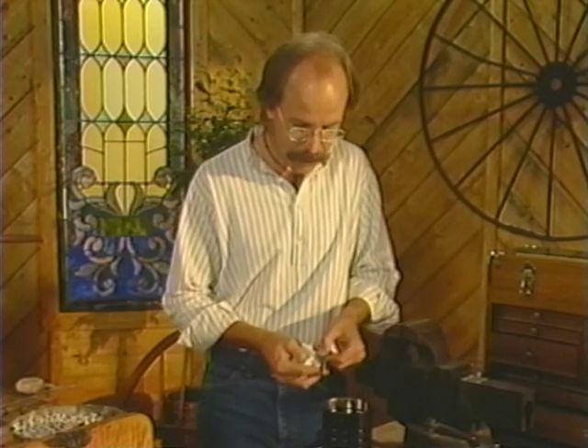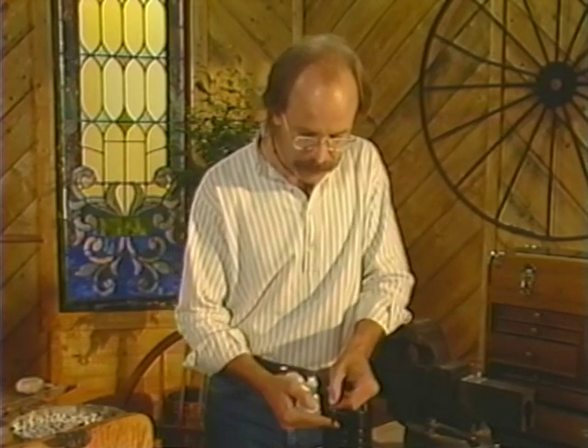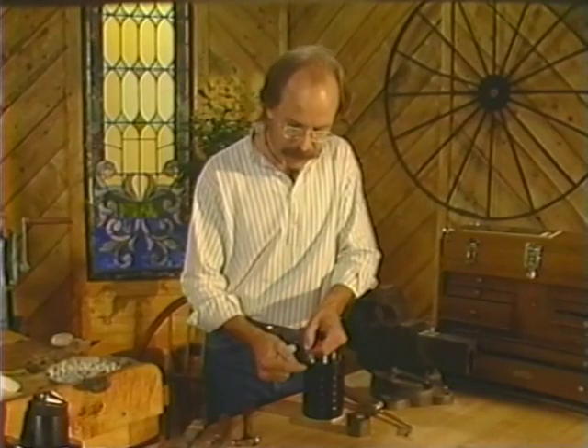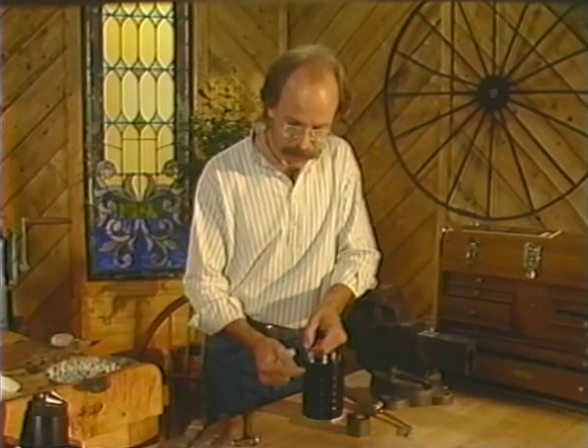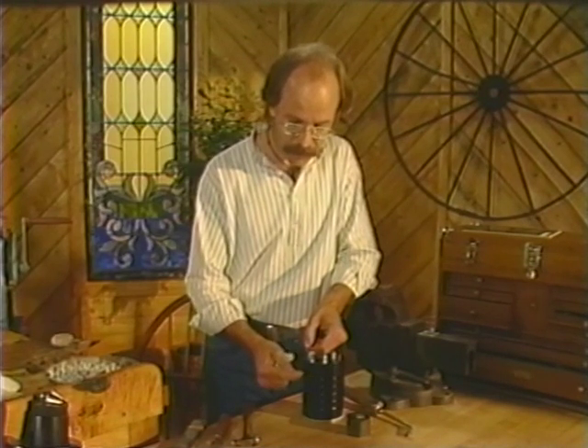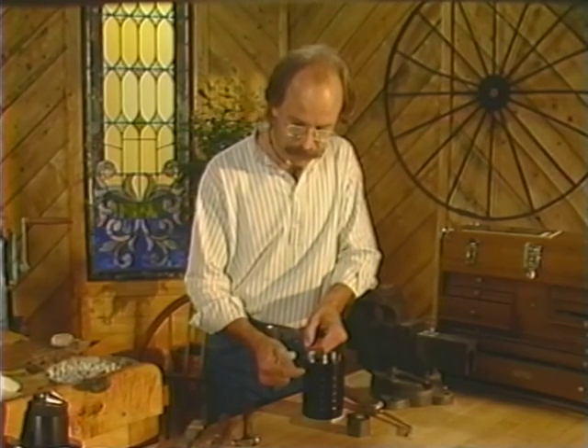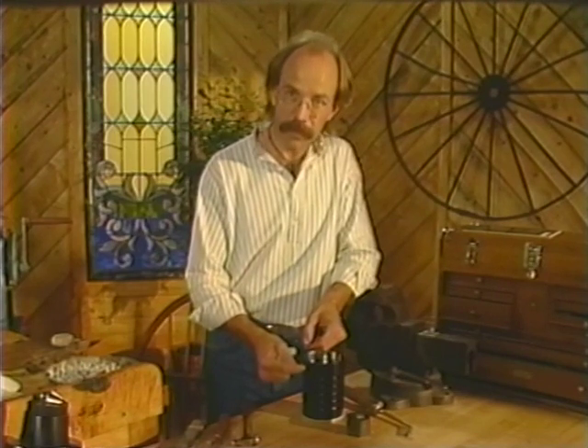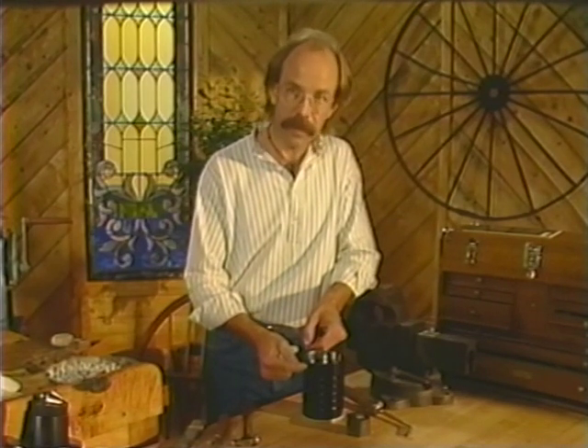And there you can see we've got yellow on the tip, which is maximum hardness, but enough flexibility to make an impact tool like this. Behind that is brown, then plum, then blue. If I had continued heating a little bit further, those colors would have advanced to the tip. The plum and the blue have the most flexibility, but at the greatest expense in hardness.